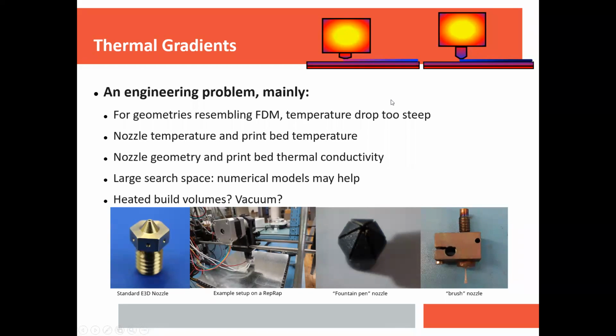There's a lot of ways to do this. You can have a laminated print bed where below the surface there's some high thermal conductivity material, but at the surface you have a very low thermal conductivity material, even a ceramic depending. The wettability doesn't even need to be that good, as long as it takes long enough of a time scale for that metal to solidify. It tends to stick to the surface. So that's one way. And then making the nozzle shorter, running some electric current, not as much as in welding, but some electric current through the nozzle helps retain the heat.